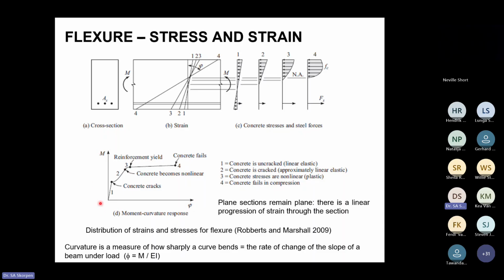And on the vertical axis, we've got the moment here. And you can see 4 points that I've plotted here. The first point is where the concrete cracks, and you can see very linear behavior until the concrete cracks. And then you get a sudden softening that's happening, so a sudden loss of stiffness as well when the concrete cracks. And now below the neutral axis, we would be ignoring any contribution of the concrete and tension, and now all of that force, that tension force, is going to be assumed to be taken by the reinforcement.